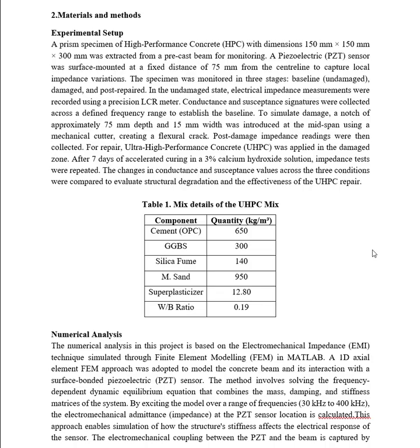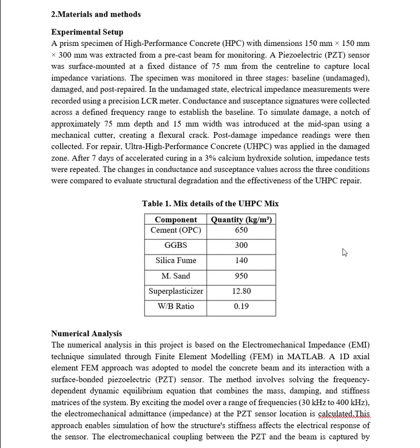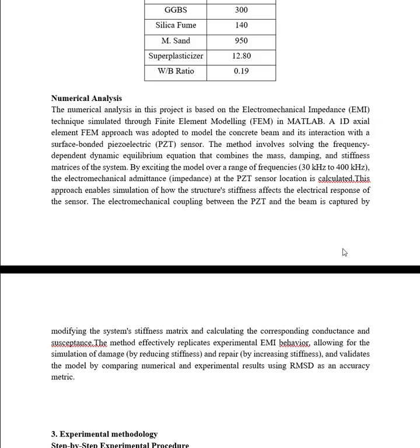The repaired specimen was cured in 3% calcium hydroxide solution for 7 days, and then the impedance readings were again recorded. We extracted conductance and susceptance values over the frequency range to analyze structural changes across each condition.